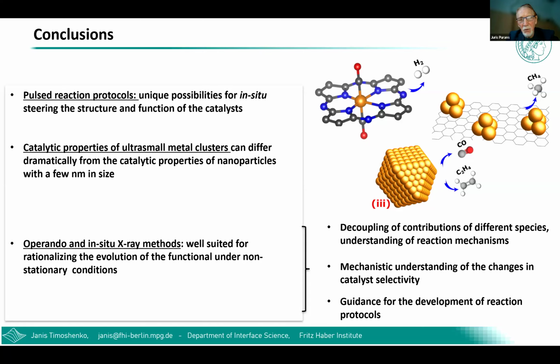In the prepared catalyst, copper is kept in place by the copper-nitrogen bonds with the nitrogen dopants in this carbon structure. So it's a very commonly observed structure. And then under applied potential, yes, it forms these metallic clusters.